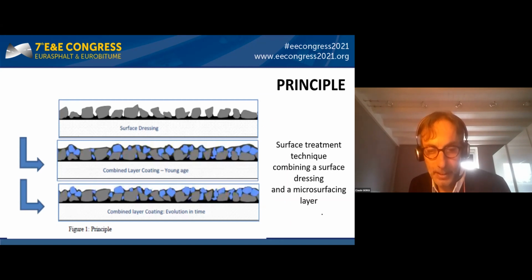This technique is composed of the following elements. A first layer of a single 6/10 or 10/14 millimeter chip seal with an open mesh of 80% is applied. A second layer, consisting of microsurfacing, will fill the gap between the aggregates of the previous chip seal to ensure sealing action. This combined layer coating makes it possible to obtain a waterproofing of the pavement to avoid the phenomenon of rejection and to guarantee microtexture over time.